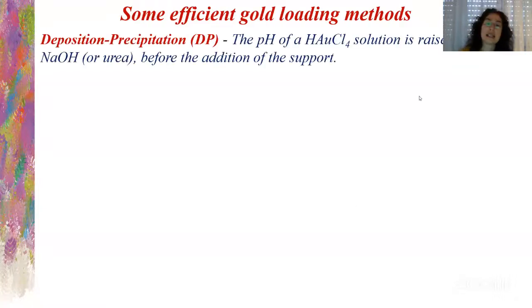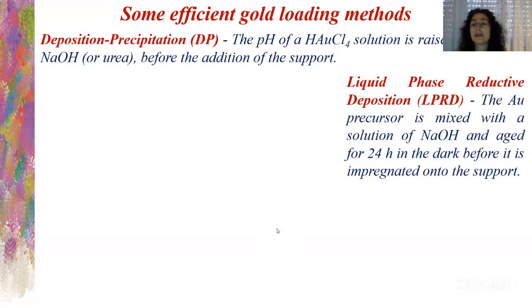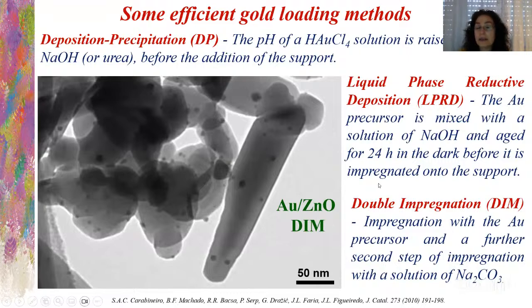Some efficient gold loading methods are deposition precipitation, for example, in which the pH of the gold precursor solution is raised to 9 or 10, depending, but 9 is usually good, with sodium hydroxide or urea before the addition of the oxide support. There is also liquid phase reductive deposition, in which the gold precursor is mixed with a solution of sodium hydroxide, aged for 24 hours in the dark, and then impregnated in the support. There can be other methods, like the double impregnation method, in which the gold precursor is impregnated into the support, and then there is a second step of impregnation with a solution of sodium carbonate.